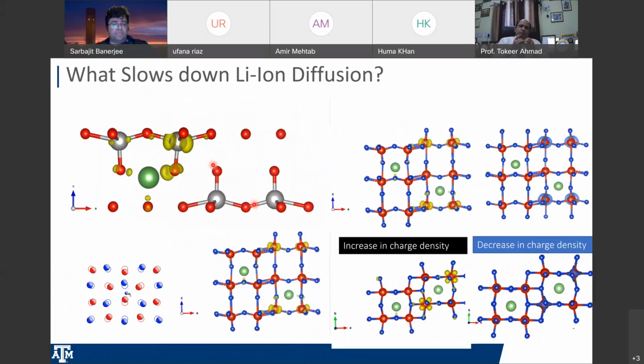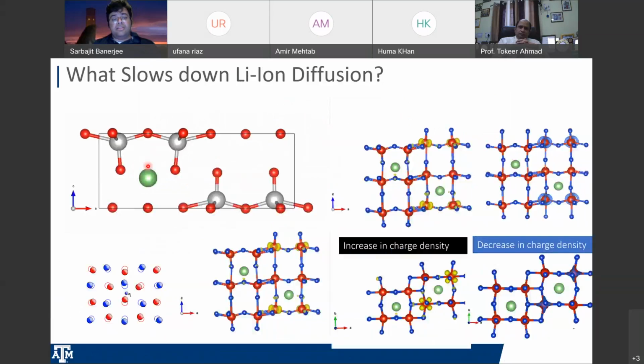And this has something to do with the fundamental nature of storing ions in large band gap transition metal oxides. We need to have large band gap transition metal oxides because that's what you get the voltage from. But then the challenge with large band gap metal oxides is that they are typically not very conductive, right? And so what happens here, if you take a look at this animation, when an electron comes in, that electron localizes on the vanadium site. And if you take a look at a charge density difference map, it traces out the contours of a vanadium 3d xy state. So the electron is localizing in a 3d xy state.